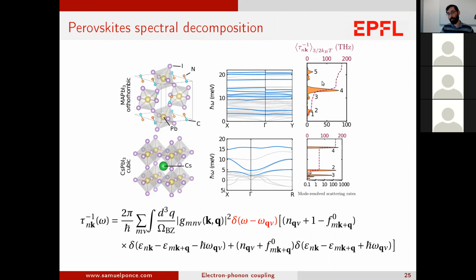And you have three main optical modes that dominate the electron-phonon coupling. I should mention that here I'm showing only the low energy range of the phonon band structure, but actually you have much higher energy states, which correspond to the vibration of the molecule. The carbon and CH bonds, of course, vibrate at very high frequencies that are not shown here. But for our purposes, it doesn't matter because those have very weak electron-phonon coupling. So all the coupling comes from those modes.